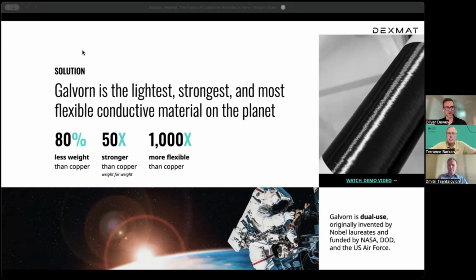So what happens when you dissolve carbon nanotubes in a solvent? They're individualized and they're very long molecules with very small diameters. And when you put molecules like that in solution, and this is similar to how Kevlar and some other materials are processed, they form what's called a liquid crystalline phase. In that phase, the nanotubes spontaneously align in localized areas. So you'll have one domain where all the carbon nanotubes are facing one direction and another domain where all the nanotubes are facing a different direction. So that localized alignment is actually done as a reduction in entropy in these solutions.